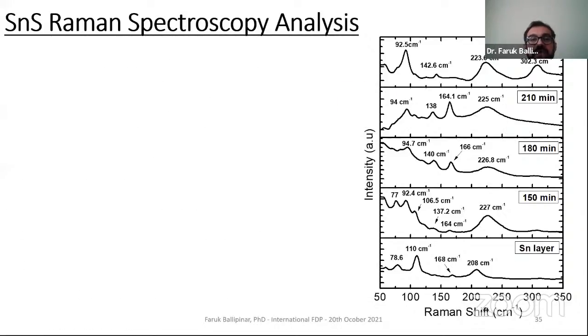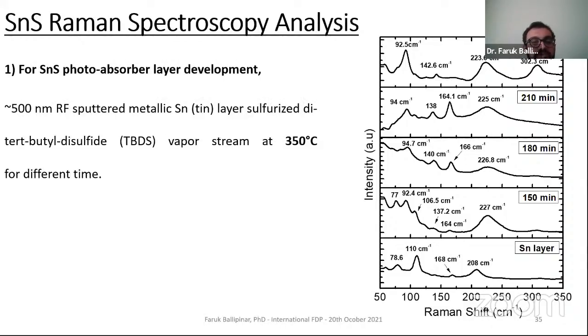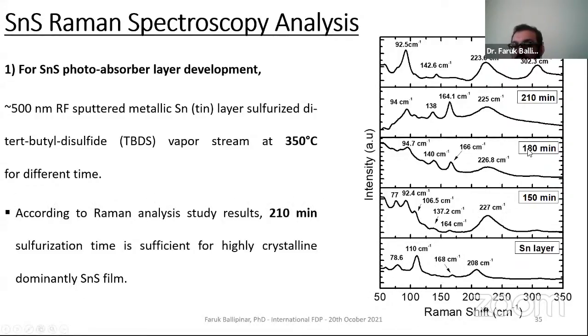So based on the results we had from the first part, 350 degrees in our experimental setup was the optimum temperature to develop initially and dominantly the tin sulfide phase, but we need a thicker layer. So instead of sputtering a 100 nanometer layer, we used a 500 nanometer metallic tin layer, again at 350 degrees, sulfurized for various times. In the Raman at the bottom side, only the metallic tin layer was analyzed through Raman spectra. After that, 150, 180, 210, and 240 minutes based on the sulfurization time.